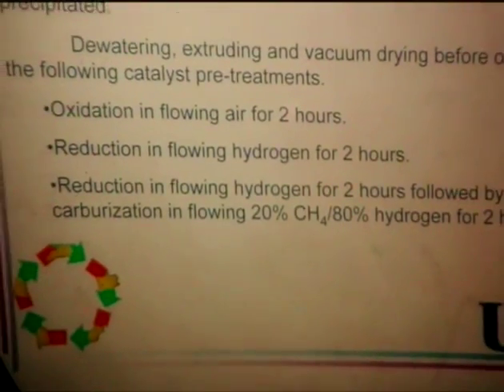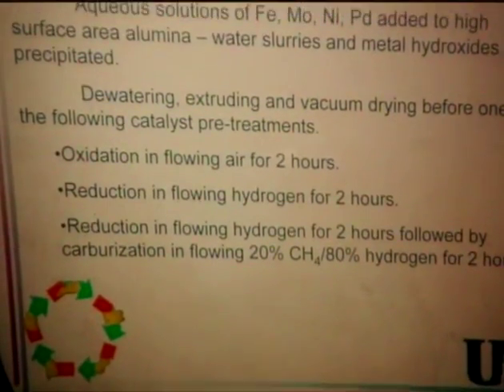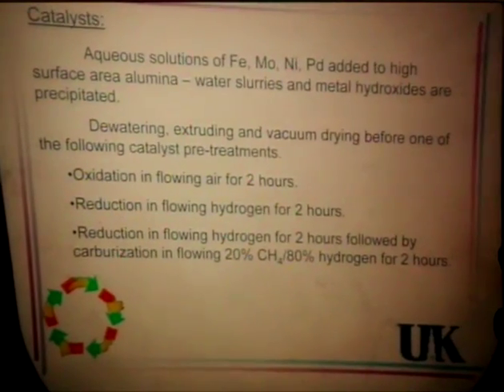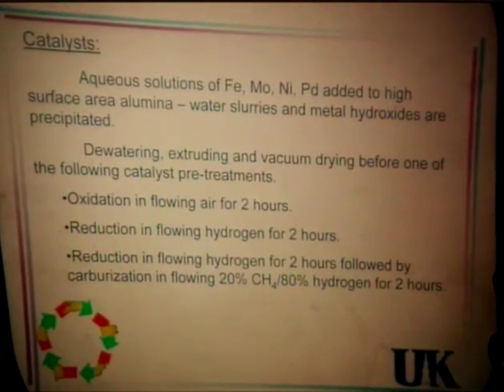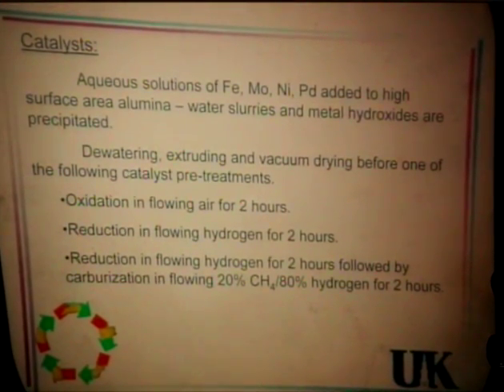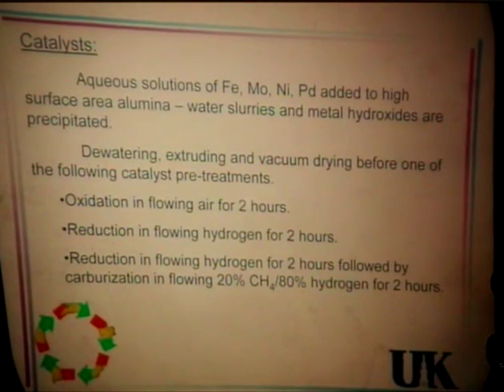For the catalyst, we prepared a metal solution added to the high surface area alumina water slurry and precipitated, washed with deionized water, dewatered, extruded, and vacuum dried. Before using the catalyst, we either oxidized, reduced, or carburized it in the presence of 20% methane in hydrogen.